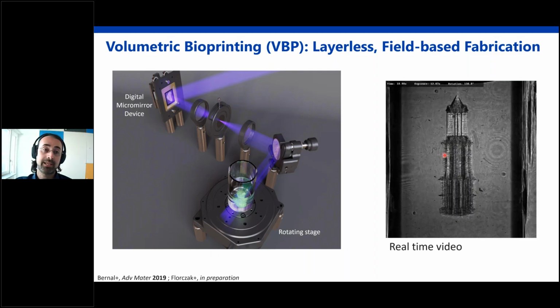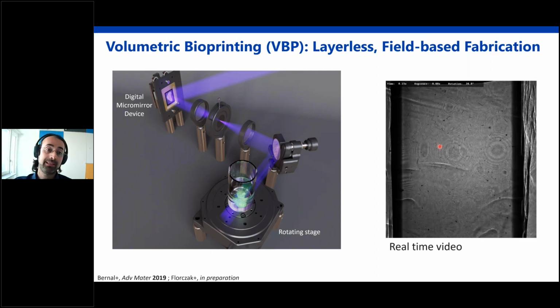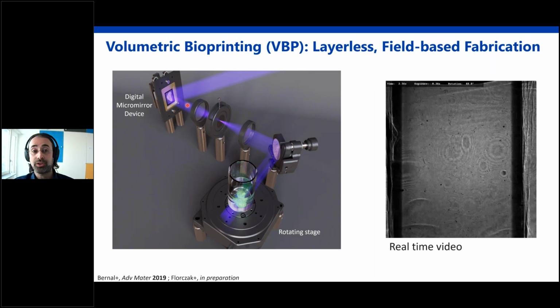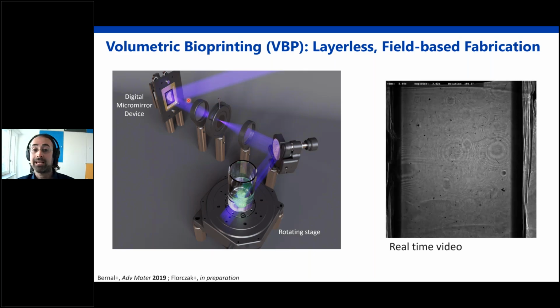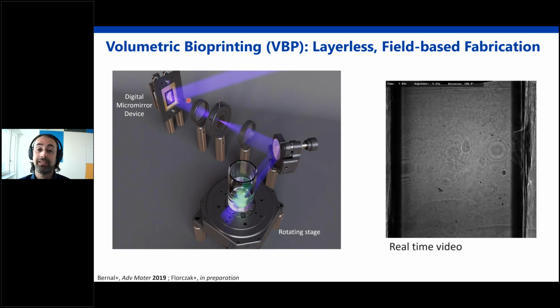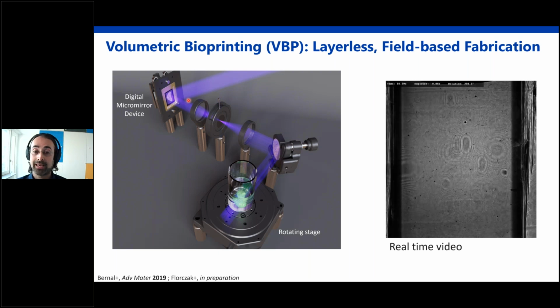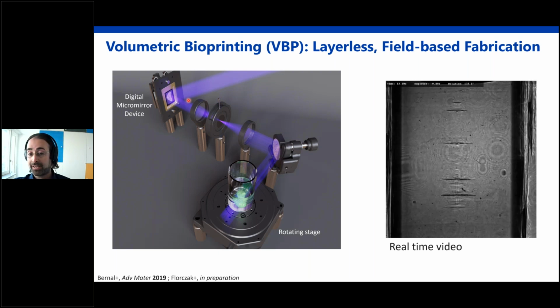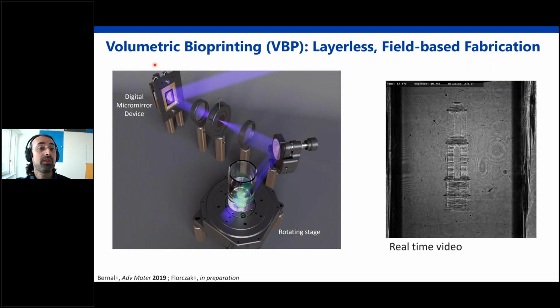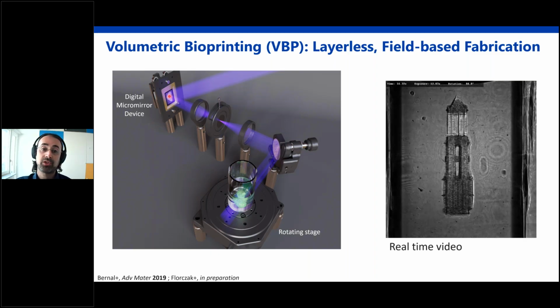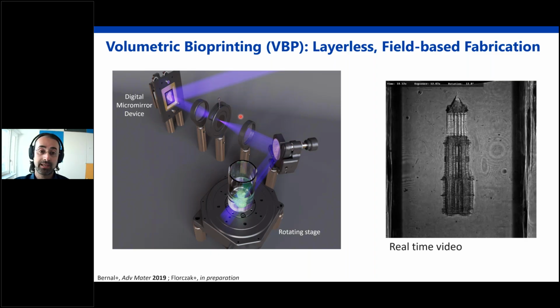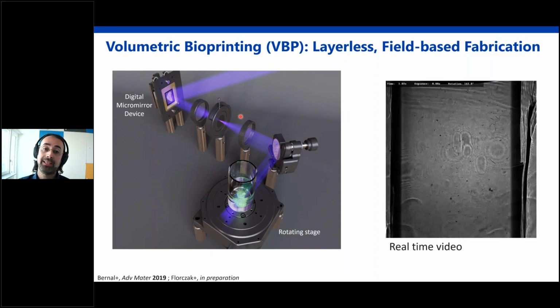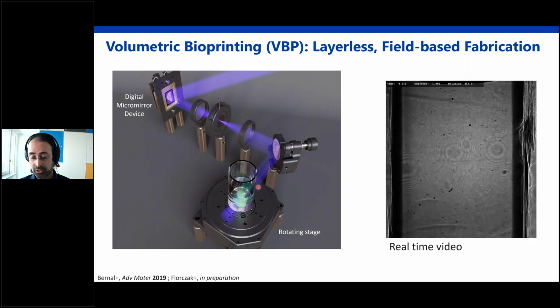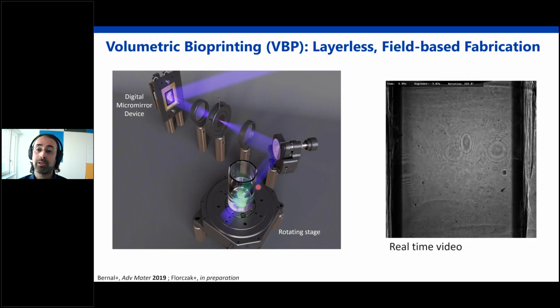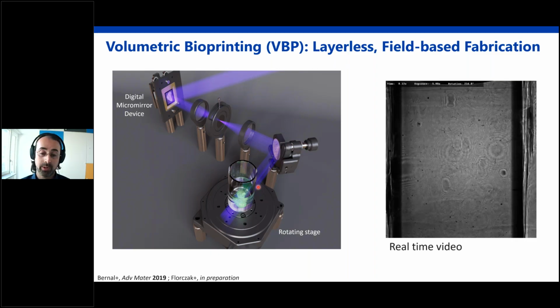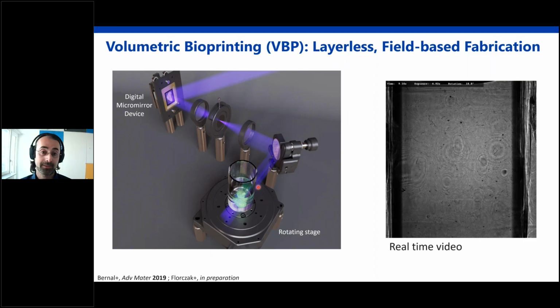So what is happening here is that we are sending visible light lasers onto a digital micromirror device, which then redirects these lights onto a rotating vial containing our photopolymer and cell mixture. The photopolymer in this case is GelMA. And what the DMD does is change the projection with every angle of rotation of this vial, so that at every angle we're sending a different 2D image, and the composition of these 2D images generates a field where the polymer crosslinks only where we want, and everywhere else it remains uncrosslinked.